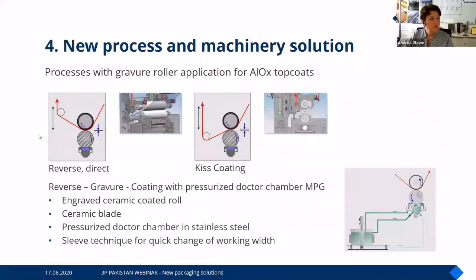For coating processes, usually we are looking into gravure methods. This can be realized in a direct contact or in a kiss coating mode. Usually engraved coated rollers are used with a ceramic blade to define the coating layer. We are working with pressurized doctor chamber systems and with a sleeve design for the opposite roller, which you see here as this black roller, to act very flexibly to changes of the working width. So to give a very high flexibility and a very fast reaction if there's any problem.